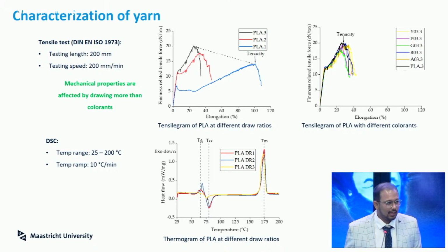In the same way, I also did the thermal stability test to see how crystalline the material is, whether the glass transition is changing, or whether there are any other changes, like different crystal structures forming. What we noticed, again in the left side picture, is that if you look at the TCC point, the curve is starting to shift more towards the left side, which means there is a small change happening, but that is because of the processing. On the right side, it looks more or less the same, which means the colorants that I added did not really affect the properties, but it's the process that I was doing.